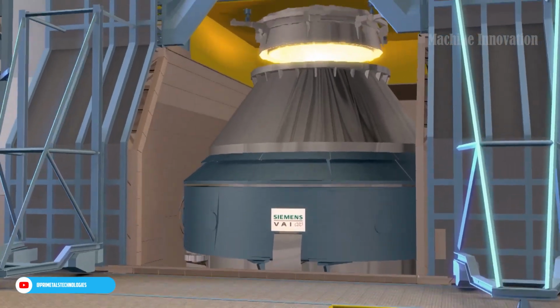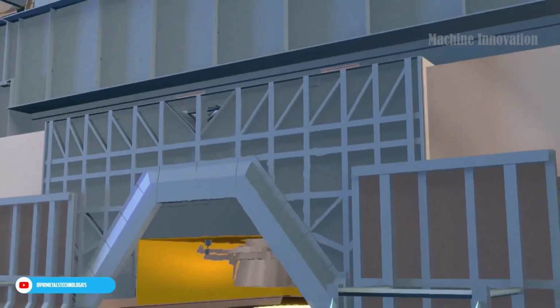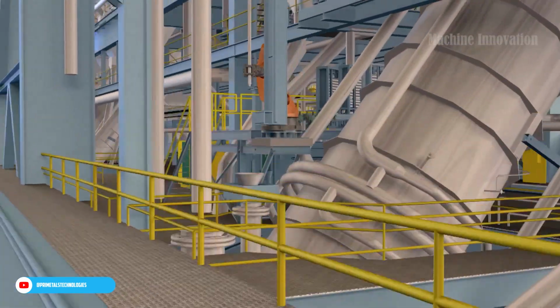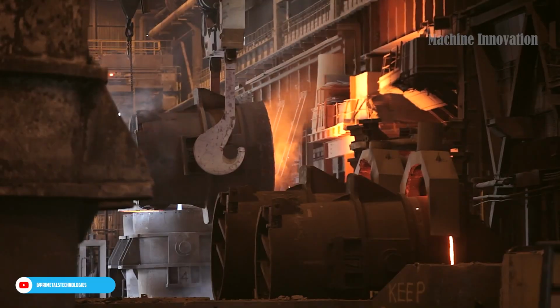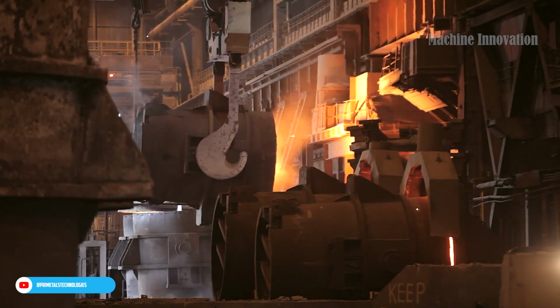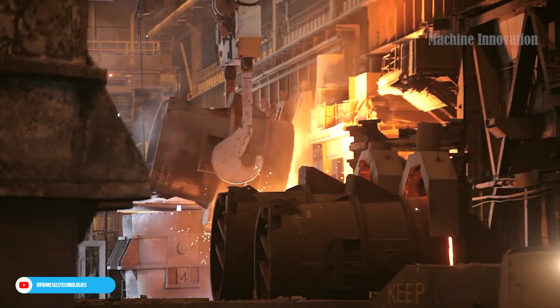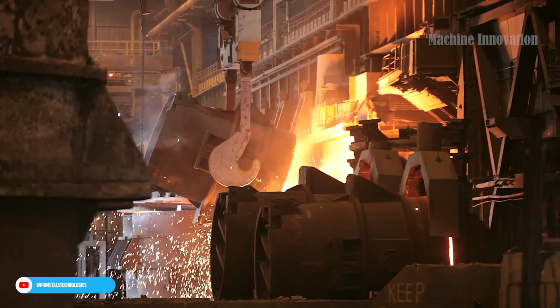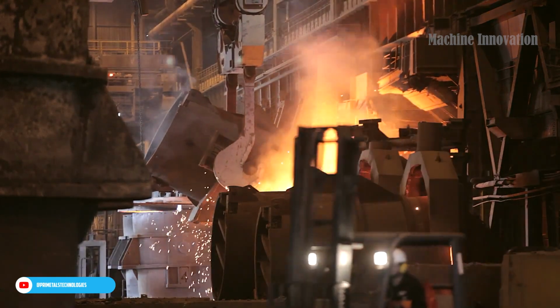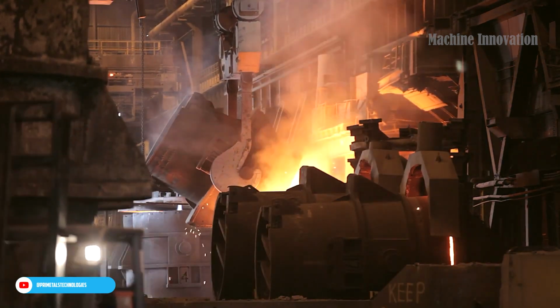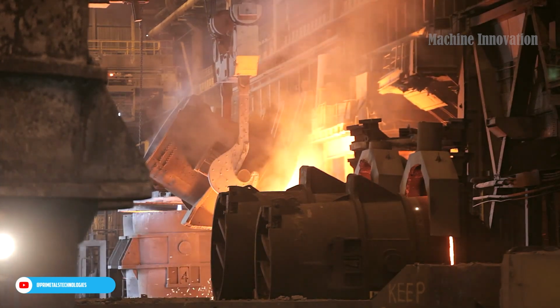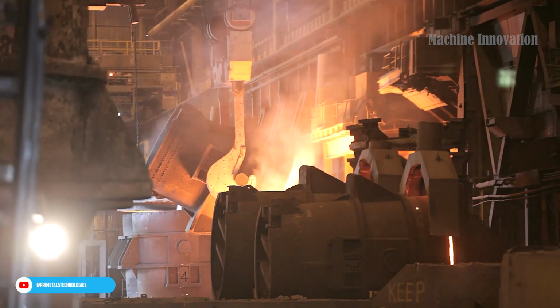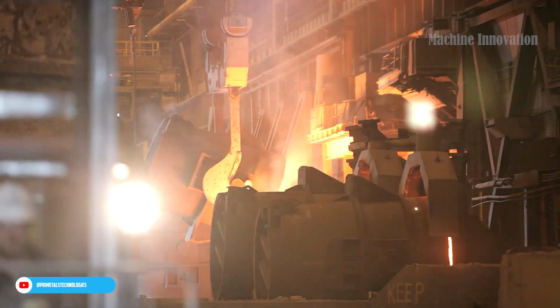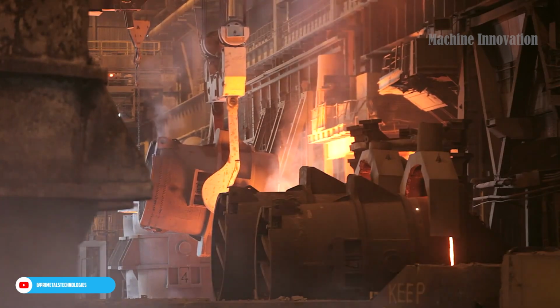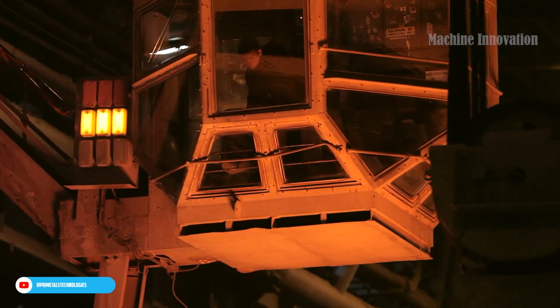With both coke and iron ore ready, the materials are fed into the plant's towering blast furnace. The furnace, heated to around 1,500 degrees Celsius, 2,732 degrees Fahrenheit, initiates a series of chemical reactions. First, the coke burns in the presence of preheated air, generating carbon monoxide, which acts as a reducing agent. This carbon monoxide reacts with the iron ore, stripping away its oxygen and resulting in molten iron, often referred to as pig iron due to its high carbon content.